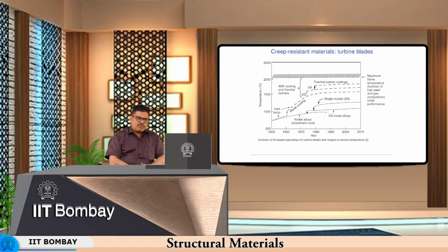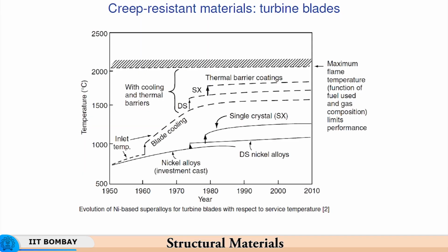Now, when we have creep resistant materials and we have to prevent them from oxidation, from environmental degradation, then it is important to apply coatings which will withstand those service temperatures, which will withstand those high temperatures. So, we need to therefore have let us say thermal barrier coatings which will generally result in relatively lower temperatures, the blades being maintained at low temperatures, and most importantly prevention of oxidation. So, both these purposes are achieved by applying thermal barrier coatings.